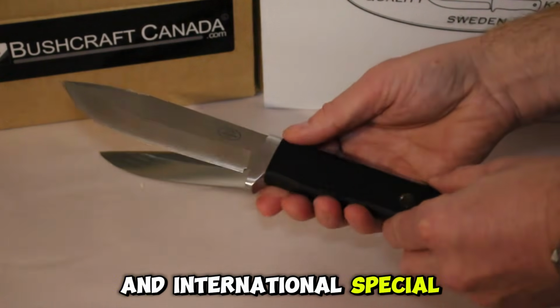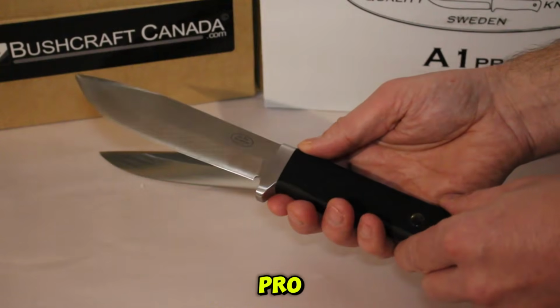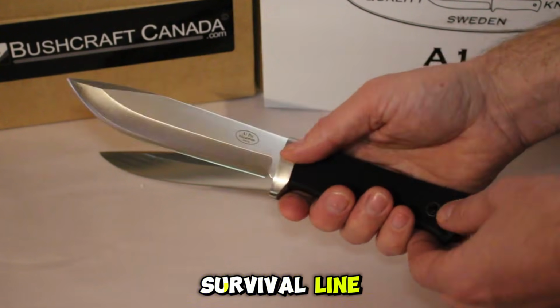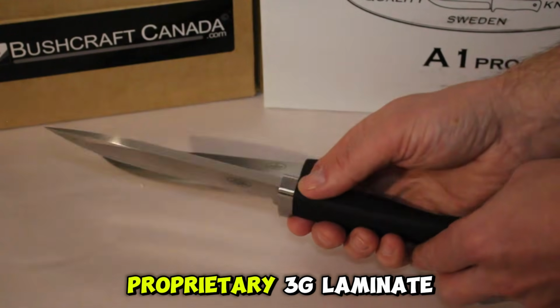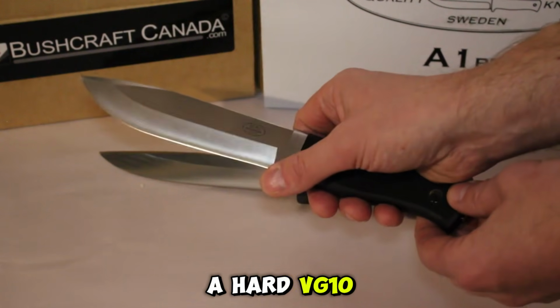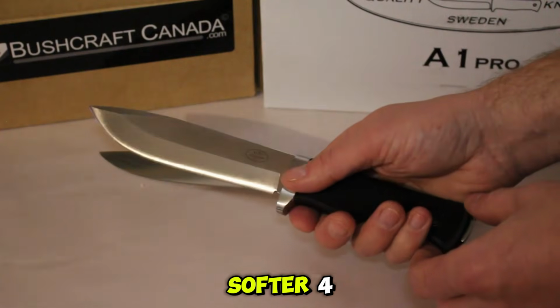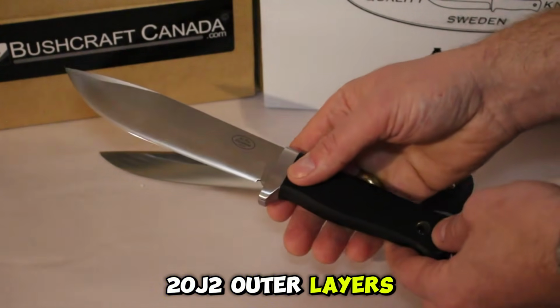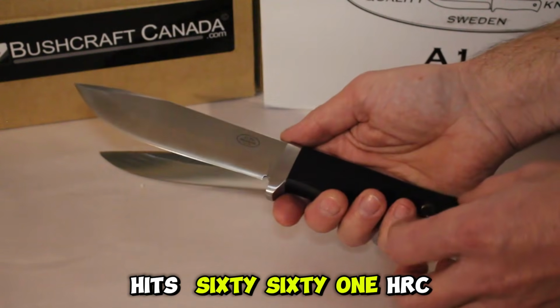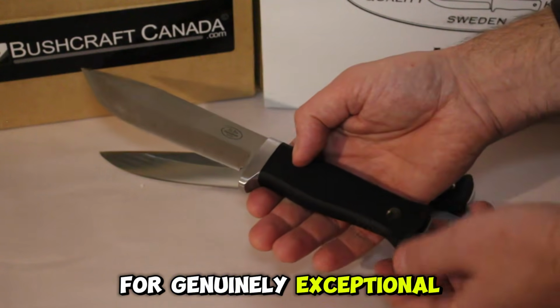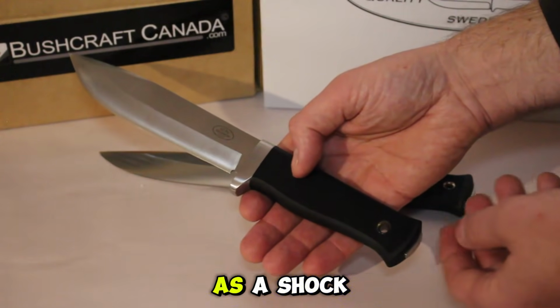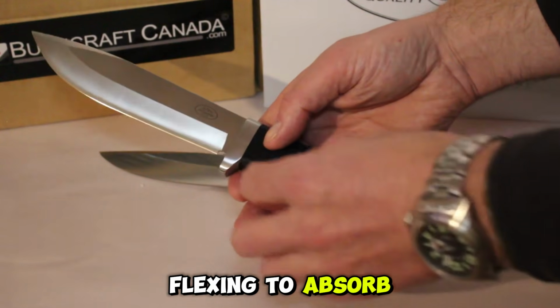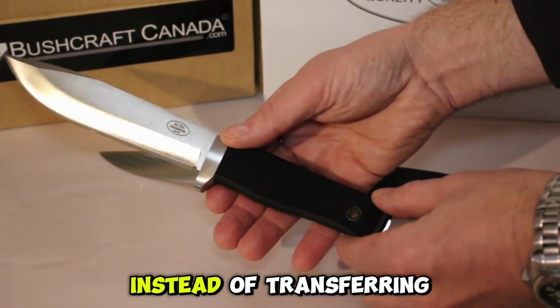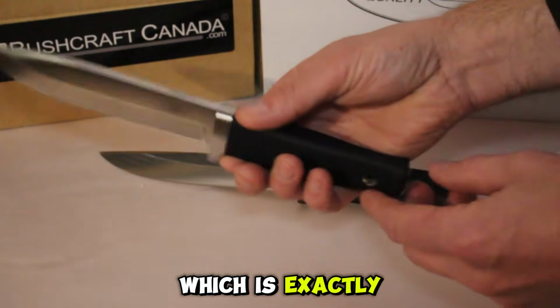Fällkniven has supplied blades to the Swedish military and international special forces for decades, and the A1 Pro is the flagship of their professional survival line. The 6.3-inch blade uses their proprietary 3G laminate, a hard VG10 stainless core sandwiched between two softer 420J2 outer layers. The VG10 core hits 60-61 HRC for genuinely exceptional edge retention, while the soft outer layers act as a shock-absorbing jacket, flexing to absorb impact during battening or chopping instead of transferring it to the hard core, which is exactly what prevents the chipping that plain hard steels suffer under impact.